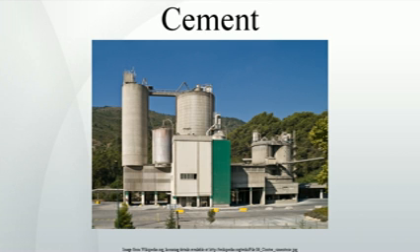Supersulfated cements. These contain about 80% ground granulated blast furnace slag, 15% gypsum or anhydrite and a little Portland clinker or lime as an activator. They produce strength by formation of ettringite, with strength growth similar to a slow Portland cement. They exhibit good resistance to aggressive agents, including sulfate.